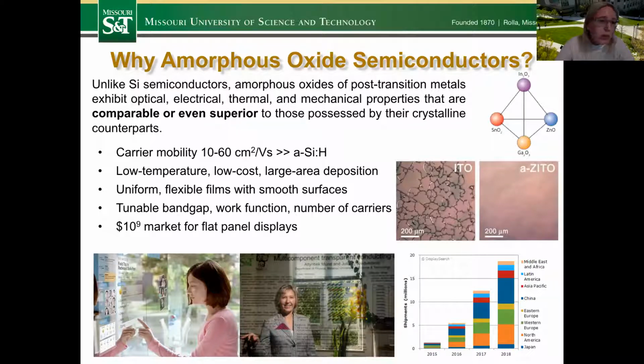They, of course, require low temperature deposition. It's low cost. We can deposit these materials in large area, uniform, flexible films with smooth surfaces. We can tune band gaps, optical band gaps. These materials are transparent in the visible. We can tune work functions with the composition, and the number of carriers can be tuned over very wide ranges, from semiconducting to very high carrier mobilities. And of course, the biggest market right now is in flat panel displays, although these materials find a lot of applications in many optoelectronic devices and beyond.